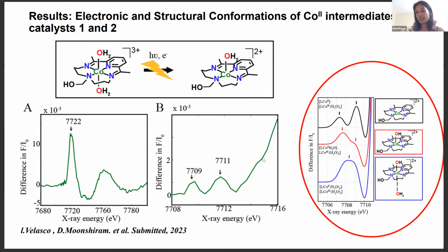So we explored various geometries, a square planar one, a square pyramidal complex, as well as an octahedral geometry. And the best agreement in terms of difference between these two pre-edges of around 2 eV was obtained for a square planar or a square pyramidal one. It was therefore essential for us to ascertain their structures for time-resolved examples.